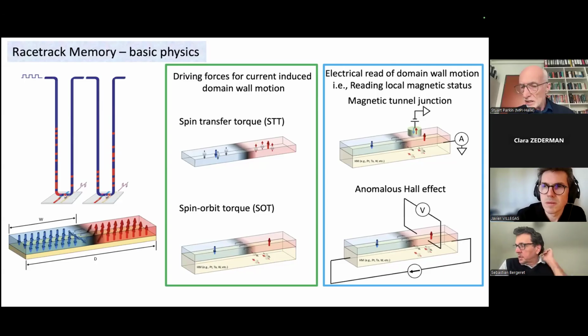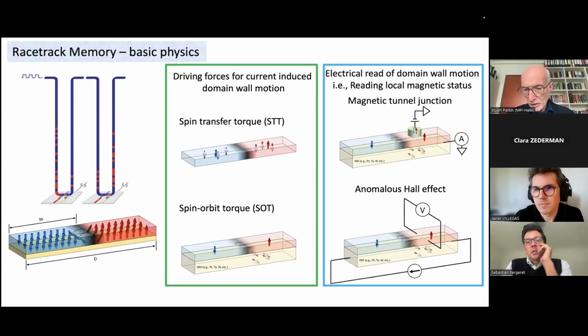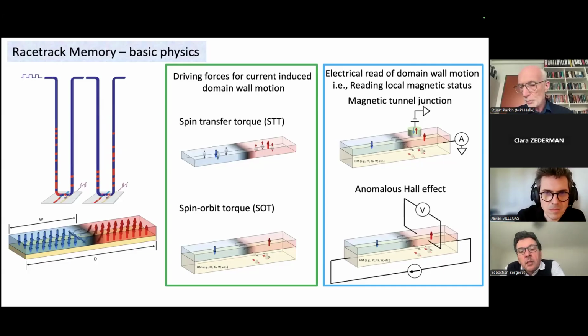torque. And in this case, the magnetic racetrack is built on this yellow layer, and this yellow layer is a layer in which charge current is converted to spin current through some kind of spin Hall effect. And typically, this is a chiral phenomenon. The charge current will develop spin current orthogonal to the direction of the charge current, and the spin polarization is orthogonal to that direction of the spin current and to the charge current.